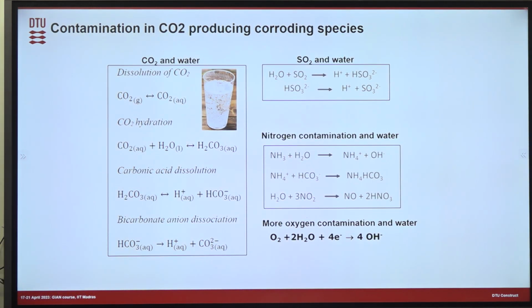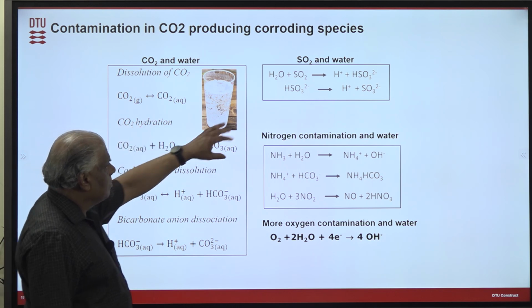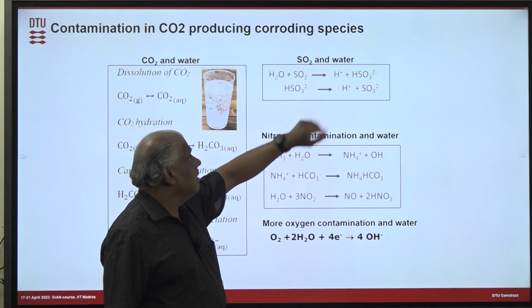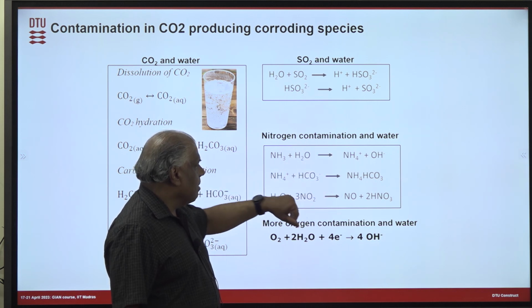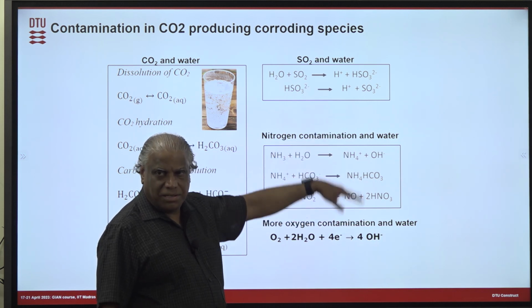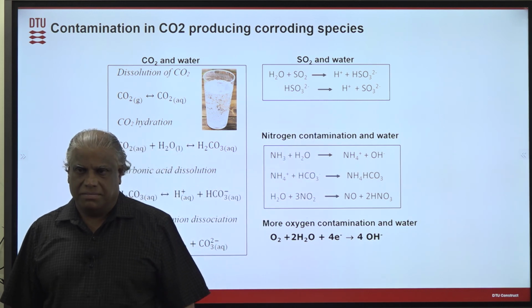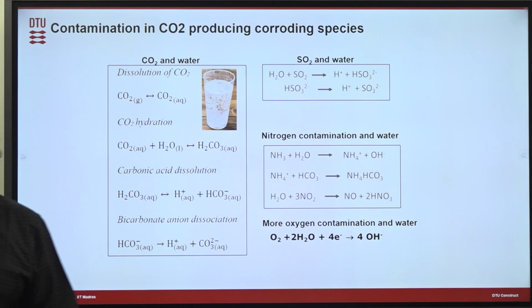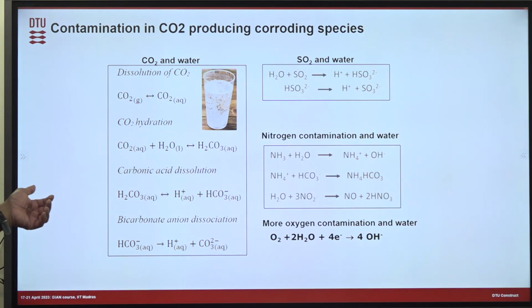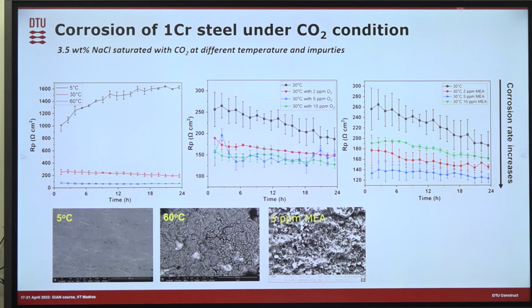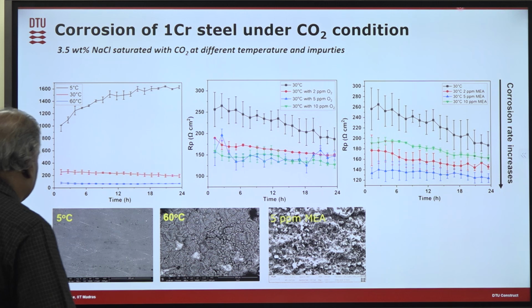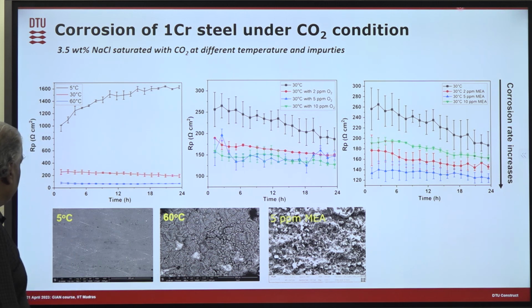So this is just showing a little bit of how the gas will dissolve into the water and create different types of acid, carbonic acid with the CO2. You get again acid species when the SO2 is dissolved, and if you have ammonia and things like that, again you get acid species, like the gases which are dissolving into the water phase. So at the end it will not exist as gas, but as species. That's what happens by dissolving into this water film.